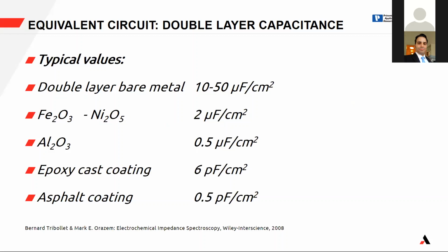So depending on the value, I found this table pretty interesting to see. For example, in bare metal, we are at about 10 to 50 microfarad. An oxide layer, we are around 2 microfarad. Aluminum oxide at 0.5 microfarad. But then you see very strong coatings, we are at the level of picofarad. So depending on how the situation is, it changes step by step.